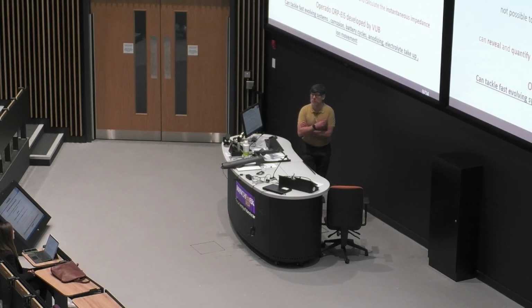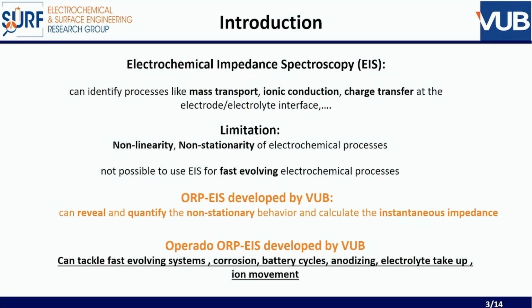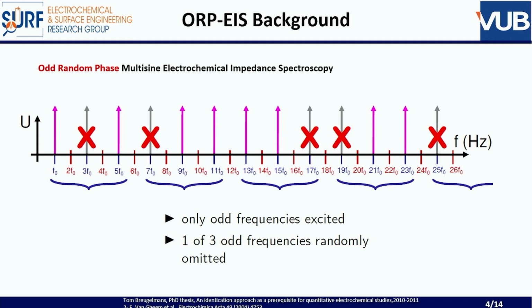It means that we can now measure the impedance while the surface is changing, which is, of course, also interesting in batteries. This is maybe a bit complicated, but I will try to explain. Instead of using a single sine measurement, we apply a multi-sine electrochemical impedance. We sample with all the frequencies, but we leave out certain frequencies. As you can see, it's a bit difficult here, so I will stand here. We omit certain frequencies, but we measure at these frequencies.